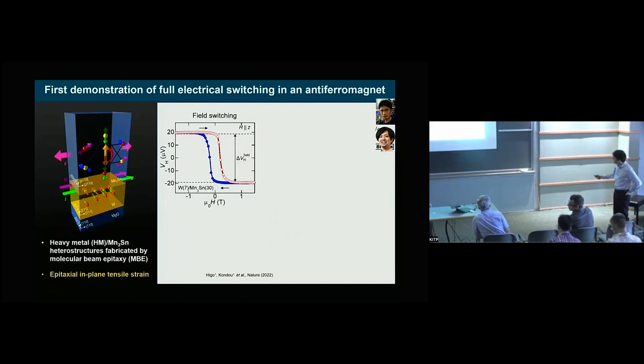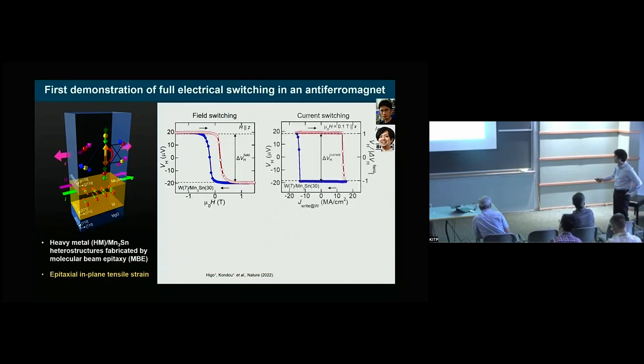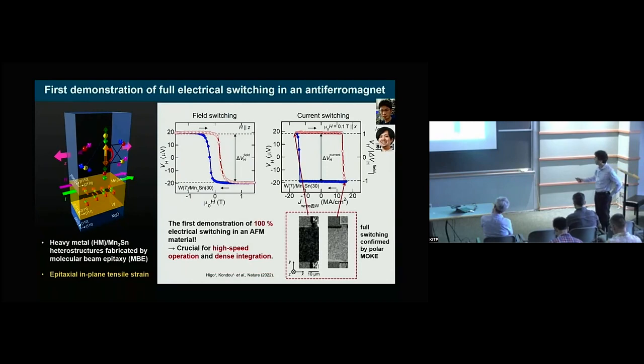And using completely the same device, we sent an electric current large enough to switch the Hall effect. And then we did see the same magnitude of such switching, with a much smaller current density than in the ferromagnetic cases. And another important point is that we have been able to demonstrate 100% switching in terms of volume, and also the 180-degree reversal.